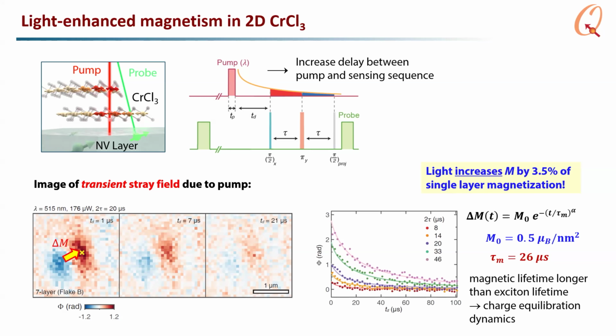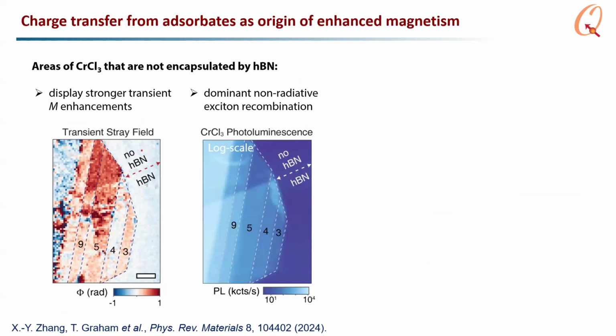One very trivial explanation would be that the laser just heats up the magnetic sample and reduces the magnetization for a little bit just by temperature. But because we map exactly what the dipole field is, and we can also map the DC field, we know that it's an increase, not a decrease. And it has a very long lifetime, 26 microseconds, which is longer than the exciton lifetime. So it suggests to us charge dynamics.